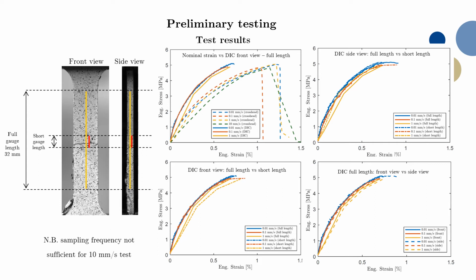Here it's possible to look at the test results. So in this picture one can see the stress strain static curves. The strain used was measured both from the front view and side view, and 2 different gauge lengths were used. One gauge length is the nominal gauge length of 32 millimeters, and the second is a short gauge length close to the fracture location. It should be noticed that the sampling frequency for high strain rate test was not sufficient for good precision of the results.